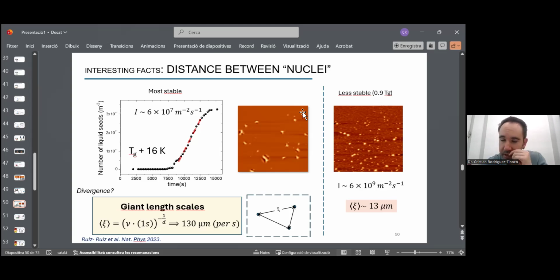Okay, so what does it mean? It means that two regions with the same relaxation time, because they have transformed into the liquid at the same time, are separated by 130 micrometers of distance, which is giving us an idea of some kind of dynamic length scale, which is very large in the case of this ultra-stable glass.